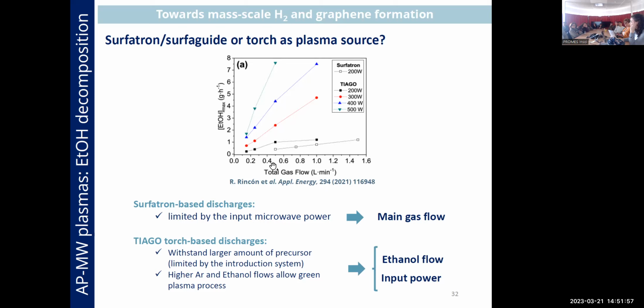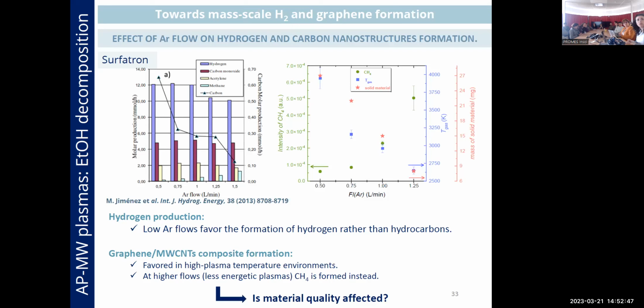So in this case, if we think about the Surfatron-based discharges, we need to keep in mind that we are limited in power. So to increase the amount of ethanol into the discharge and then maybe have more hydrogen and more material, it's necessary to play with the main gas flow. In the case of the TIAGO torch, these kinds of discharges can withstand a larger amount of the precursor, and keeping in mind that with higher argon and ethanol flows we have a green process, it's time to play with ethanol flow and input power. Okay, so let's start by playing with argon flow in Surfatron discharges.